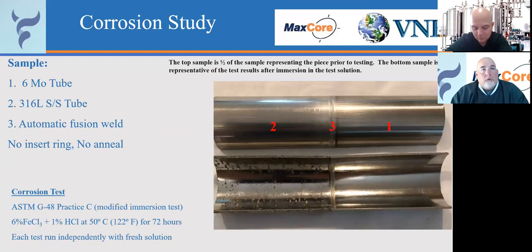And do you need to use a weld insert ring? Some people will tell you, yes, you need to use a weld insert ring. Some people want to sell you weld insert rings. I tell you, I don't think that you do. And the reason being, if you look at this particular weld, you're going to see the attack of the corrosion took place in the 316L side. It didn't take place in the weld. It didn't take place on the AL6XN material. It took place on the heat affected zone side of the 316 stainless steel.